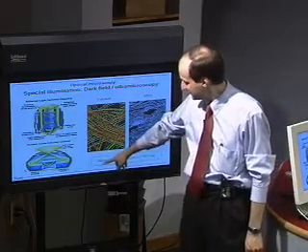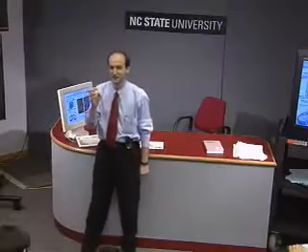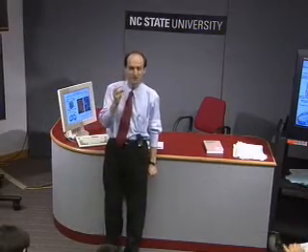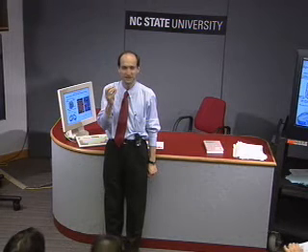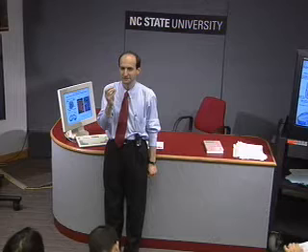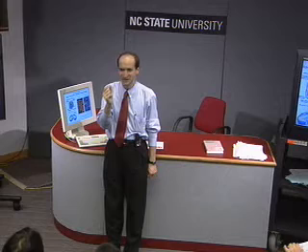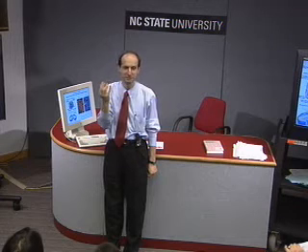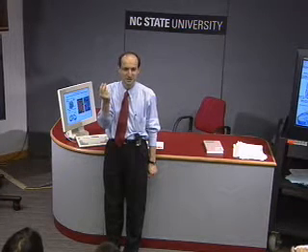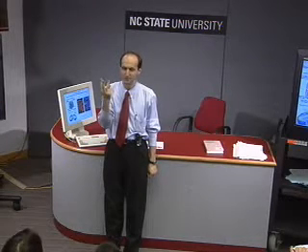Now, sometimes you can see objects which are smaller than 100 nanometers. If you have metallic nanoparticles, they shine so bright that you can see them in this way. However, what is the restriction of this method? You still have the restriction of the numerical aperture. You can see a 10 nanometer metallic particle, but usually the objective wouldn't allow you to resolve features smaller than 500 nanometers or so. So you don't know whether the bright dot that you see is one particle or two particles or five particles.